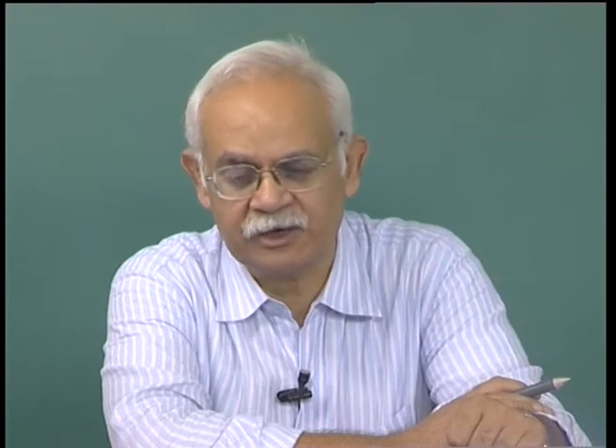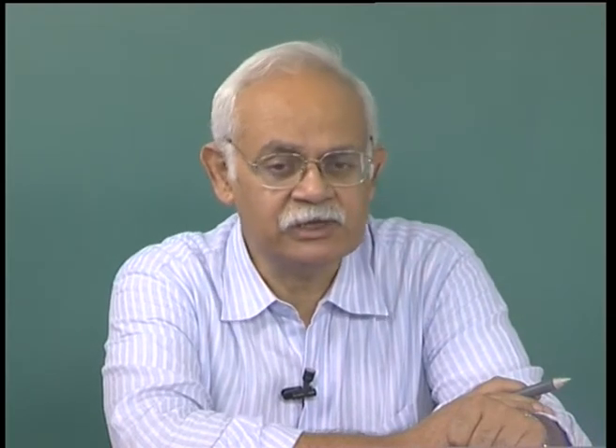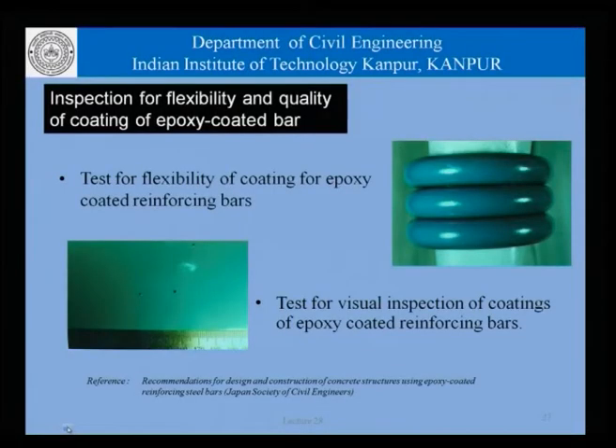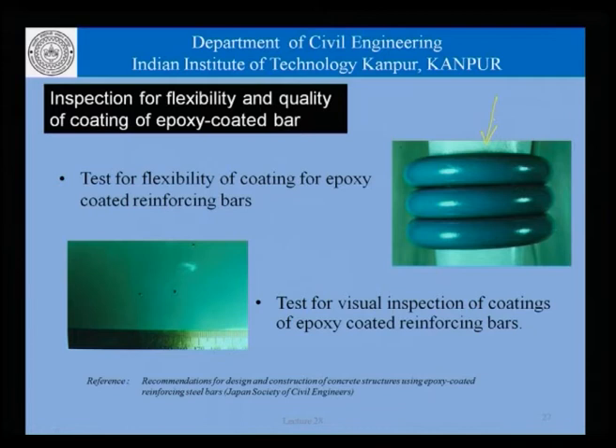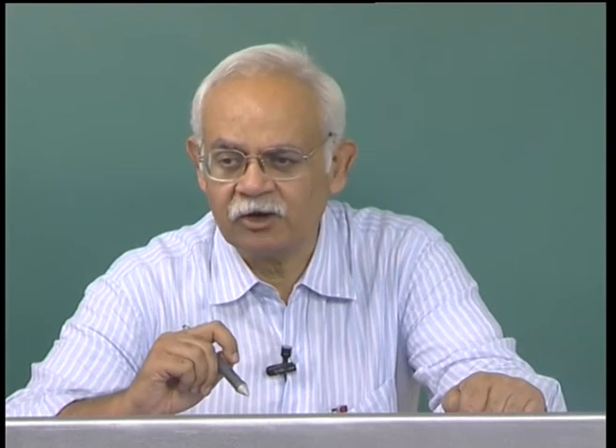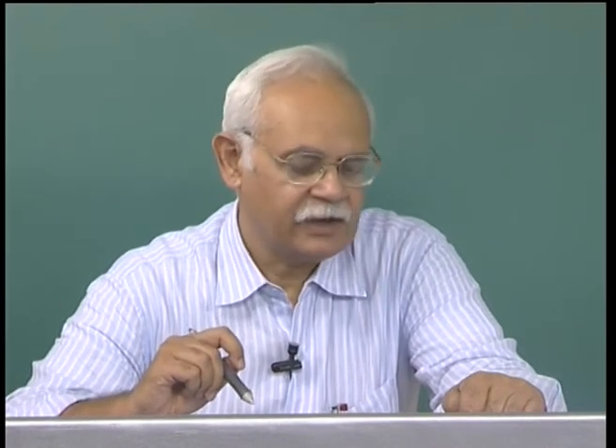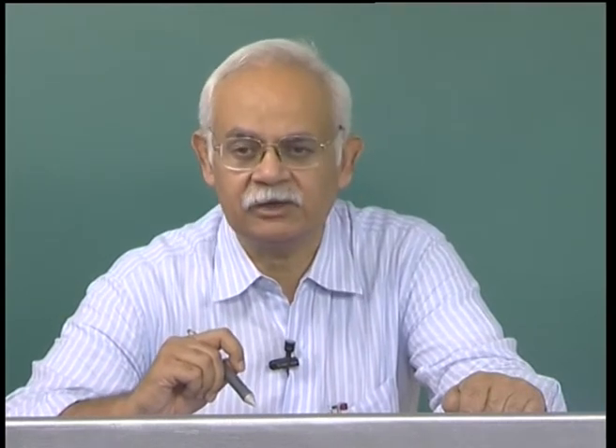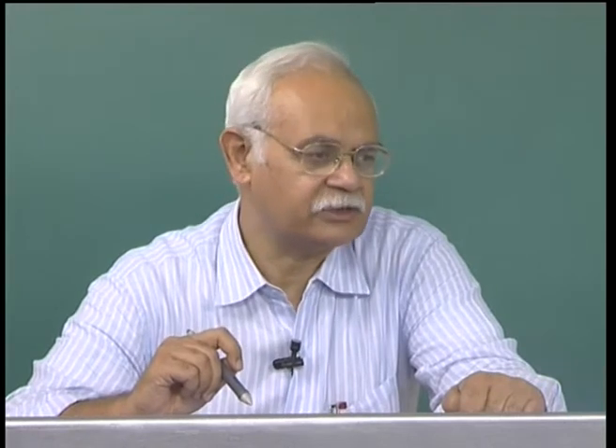Cost is a very important parameter when using any new material. Other test methods include a flexibility test and a visual inspection of the coating quality. On close inspection of a coated surface, small droplets — much like those seen on a painted surface — may be found, and the presence of these is an unacceptable sign as far as quality of the epoxy coated bars is concerned.